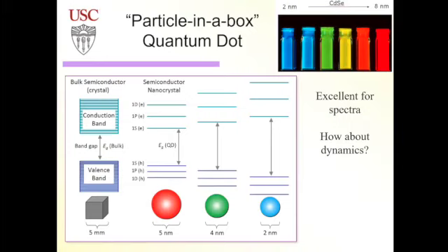If your size is smaller than the distance between electron and hole in the bulk semiconductor, then the band gap depends on the size. In the very simple model, you just say, I have an electron with some effective mass, and I solve the particle in a spherical well model for that particle, and you get energy levels, which would be S, P, D, just like the hydrogen atom. And the smaller the particle, the larger the energy gaps. And this describes spectroscopy of quantum dots very nicely.